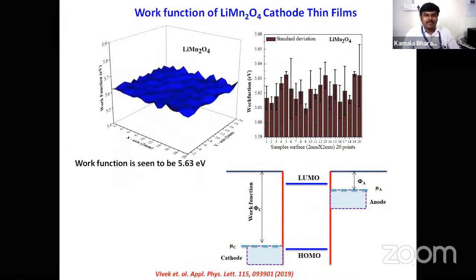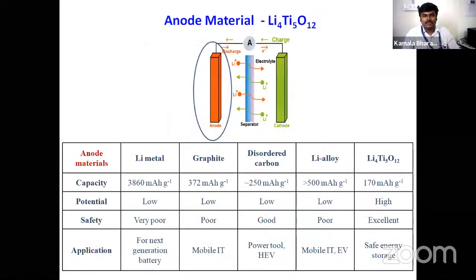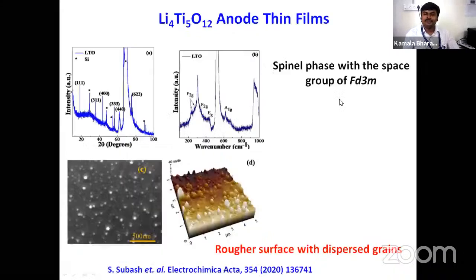Again, we measured the work function of this material, the thin film, which is found to be around 5.63 electron volt. Okay, now, I have shown a couple of cathode thin films. Now I will move into the anode material. We work on several anode materials. Now I'll show only one example, which is lithium titanium oxide.